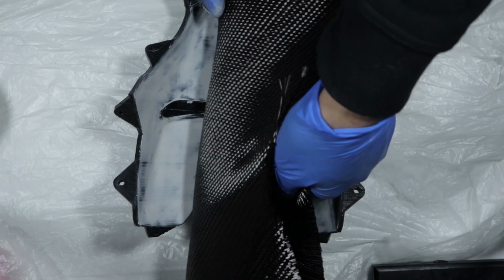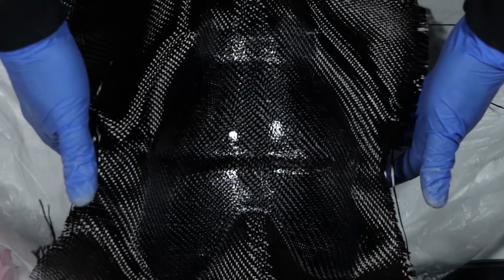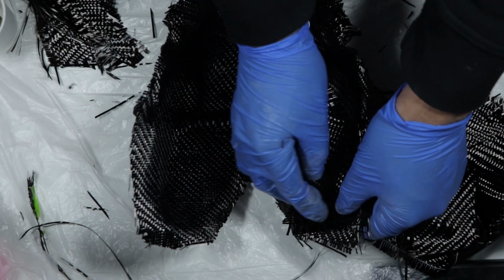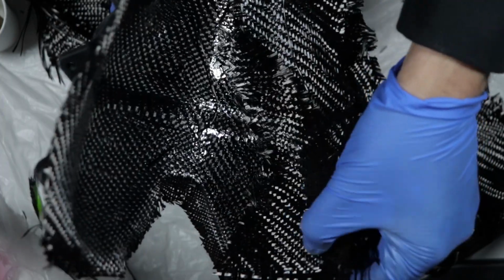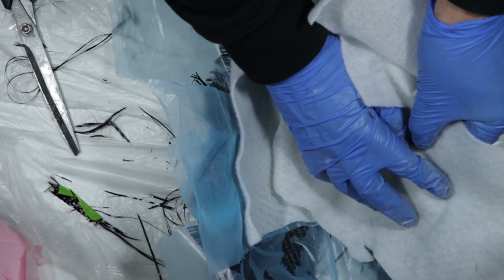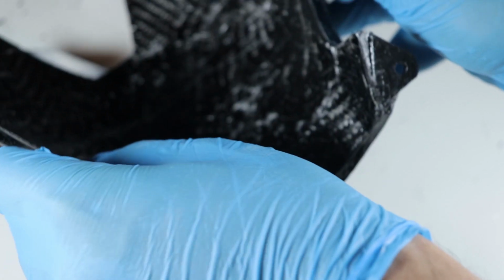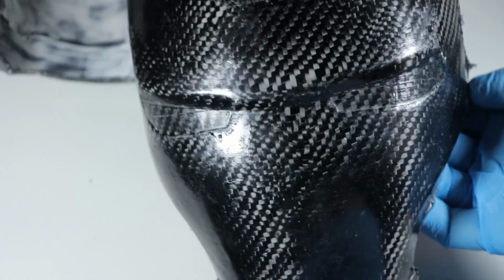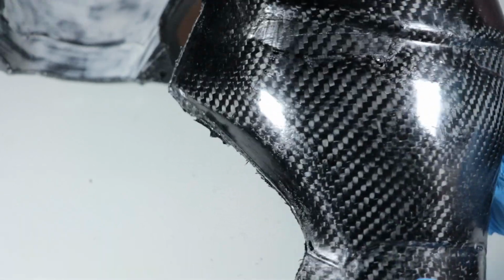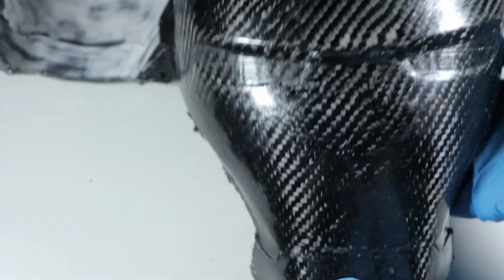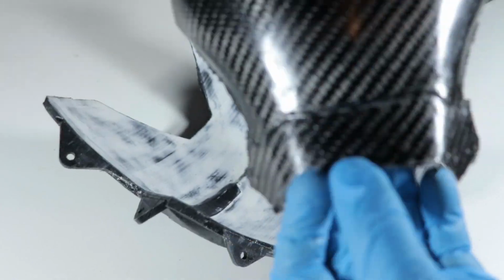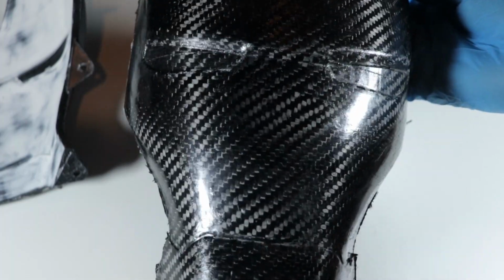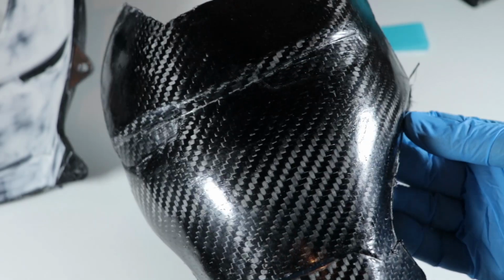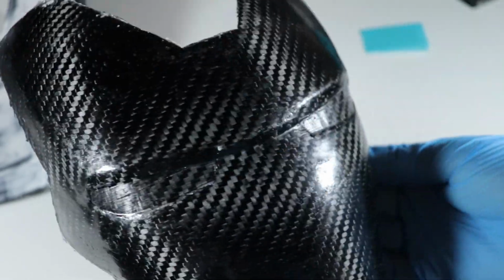To make the carbon fiber faceplate, I do the same thing. I apply one layer of carbon fiber, cut the excess, and reuse it to make the part stronger and stiffer. Then I add the release film and the breather and put it in the easy vacuum bag. The results came out pretty nice, but not so much for the first one. I'm not sure what happened here. The weaves are way too deformed, but the second one is just fine. To have a perfectly flat surface, free of pinholes, you need to sand and add layers of clear coat or varnish multiple times. Now let's make the rest of the helmet.